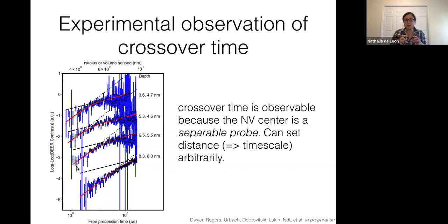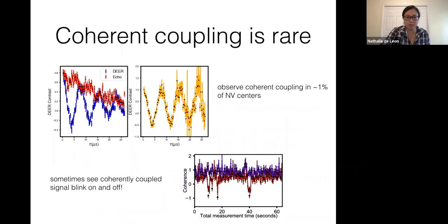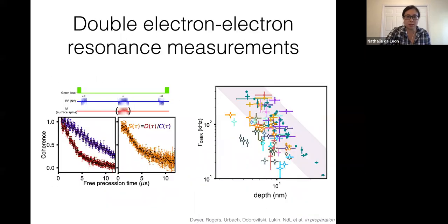So the reason that the error bars are large to begin with is because, if I go to the DEER, the way that we take this data is we take a Hahn echo, and then we take a DEER echo, right? And then our signal is this divided by this. So if these two curves are very close together, then you have very large error bars. So at the beginning of the decoherence, you have large error bars, and then at the end, you don't have any signal left, so you have large error bars again. Okay, understood. Thank you.